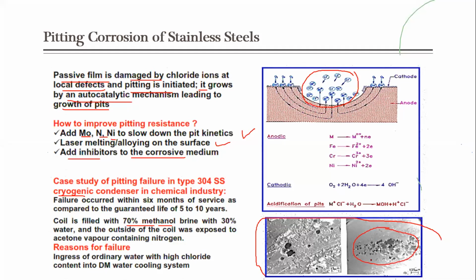Okay, they had 70% methanol brine solution with 30% water. The water that they used in their condenser had high chloride content, which led to this pitting corrosion. The main reason for failure was ingress of ordinary water with high chloride content. Okay, because of high chloride content in the water, the condenser which was designed to give service for 5 to 10 years failed within 6 months. Okay, hence care has to be taken while selecting the alloying elements in order to get good corrosion or pitting corrosion resistance.